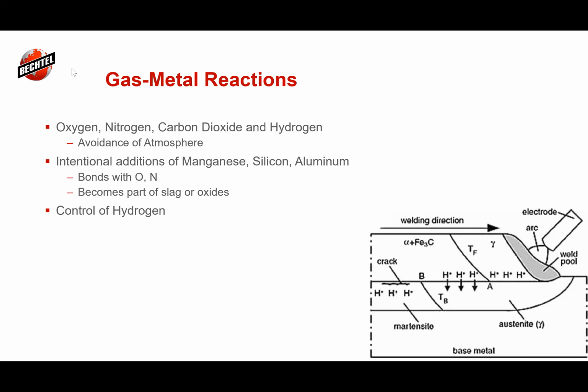And if we make that heat affected zone the weak link, which is really narrow, that's typically where we get things like the underbead cracking, where the hydrogen will have a tendency to go to the fusion line and the heat affected zone. And that also can be a susceptible microstructure, like we talked about with the martensite. This is a really nice diagram that talks about how hydrogen can affect our high strength welds, particularly when we're dealing with anything, but definitely when we get into the A514s with the carbon steels. You want to make sure that you're using low hydrogen electrodes, and you're buying from a really good source for your weld metal, something that's going to have low hydrogen and low impurities,